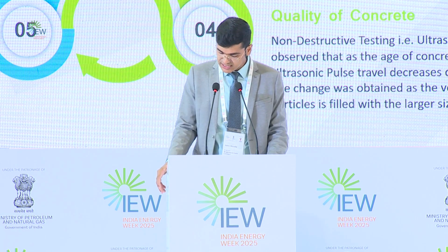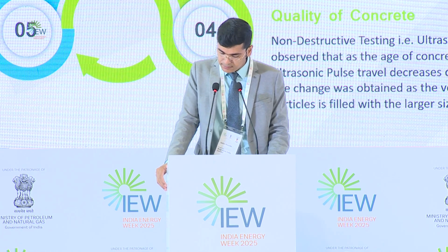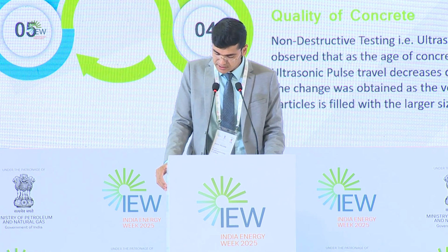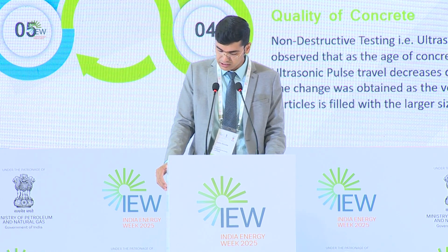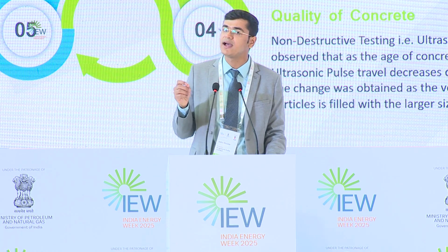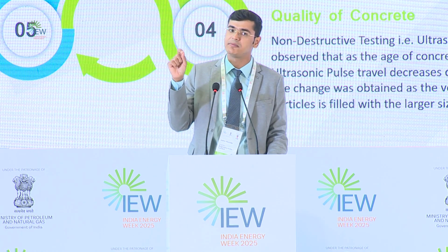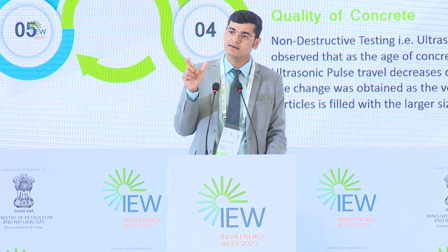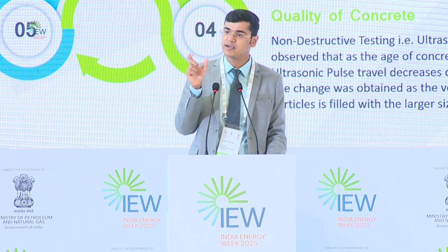The percentage change in strength parameters: increase in flexural strength of specimen is more than the percentage increase in the compressive strength. And this is owing to the fact that it is a fibrous and elongated material. It is as good as a reinforcement itself, but at a smaller scale.